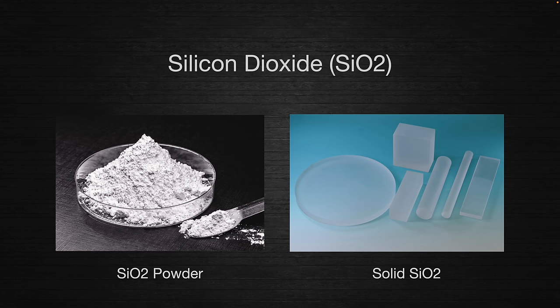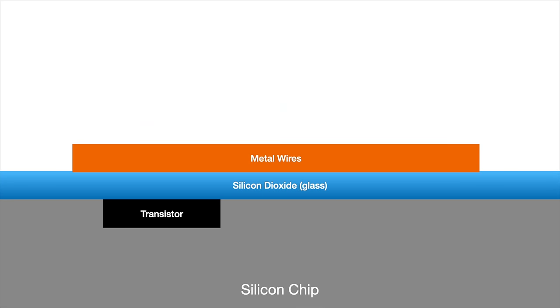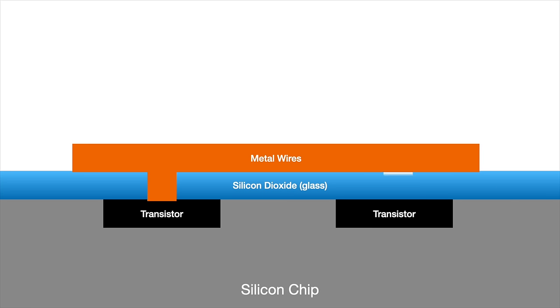This was the missing piece of the puzzle. Now, you could grow an insulating layer of silicon dioxide directly on the surface of the chip. Metal wires could be added on top, and they would be insulated from the silicon substrate below. Holes in the oxide layer would be used to define exactly where the wires made connections to the silicon devices, which meant that for the first time, researchers could put multiple interconnected devices on the same chip.